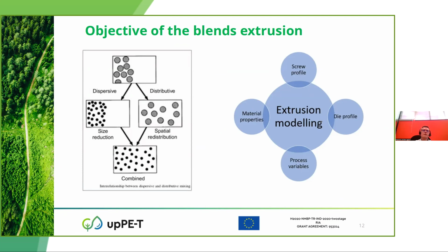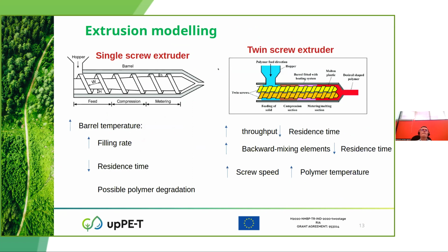And what does all this depend on? The polymer must be processed above its glass transition temperature, but below its degradation temperature. The blend should also be processed above its melting temperature in case the polymer has some degree of crystallinity, and the temperature also influences the melt's viscosity. A low temperature results in high melt viscosity and high torque. An elevated temperature reduces the torque due to lower melt viscosity, but it increases the risk of polymer degradation.